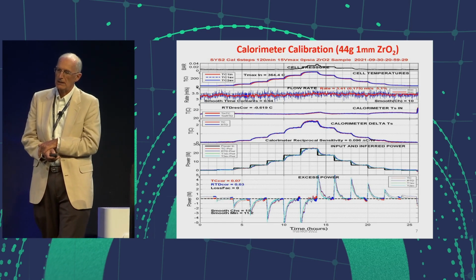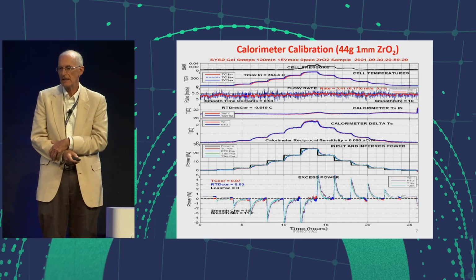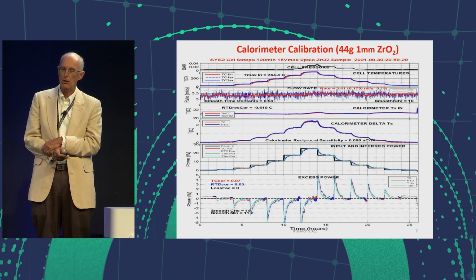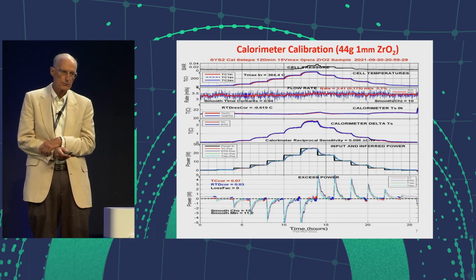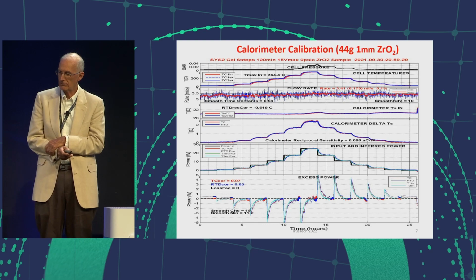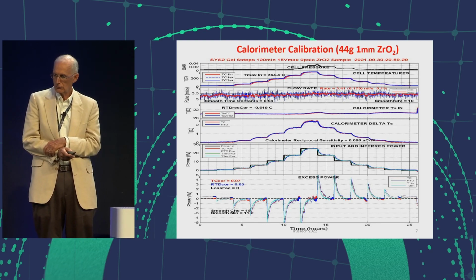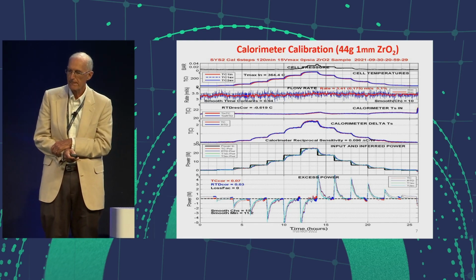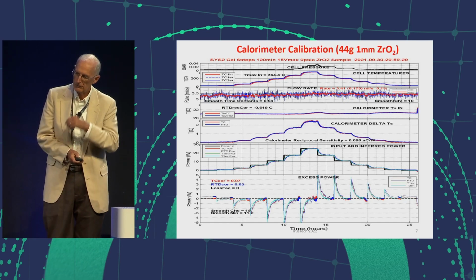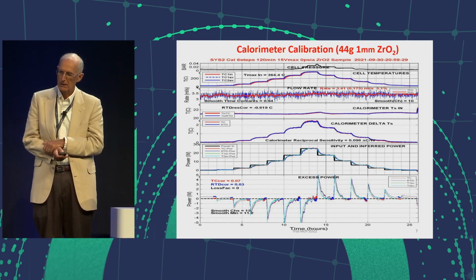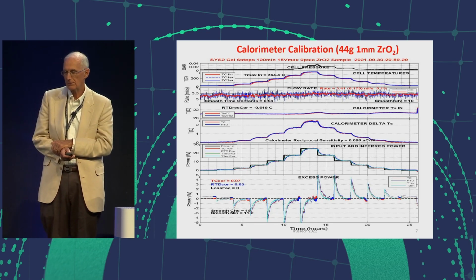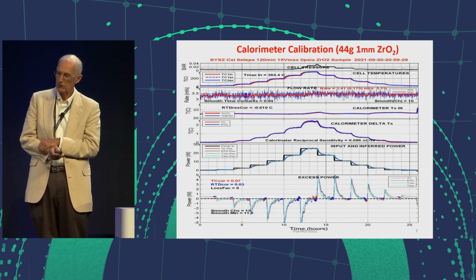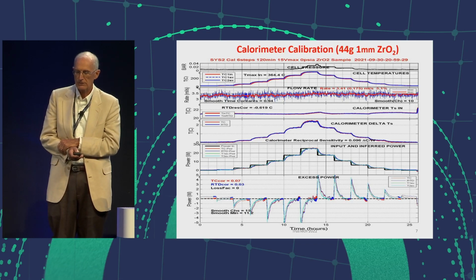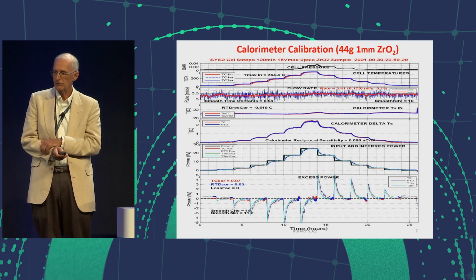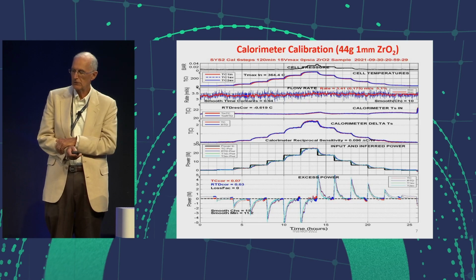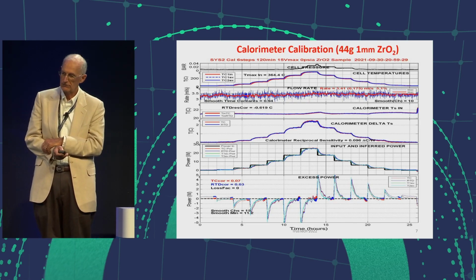This shows the calibration data that's taken. The calibration is done by an automatic sequence. It steps through 10 or 12 different temperature differences. In this data, it took about 26 hours to do. The first graph up there shows the pressure, the second, the temperature of the cell, the third, the flow rate. The fourth is the temperature differences. You see the temperature differences, even for temperatures of the cells over 300 degrees, are only a couple degrees C.